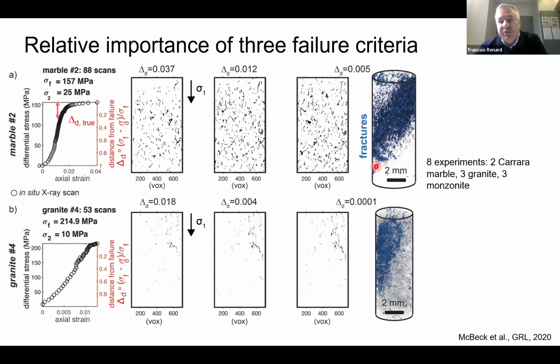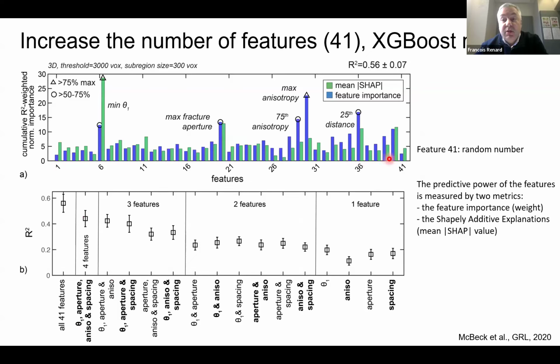And instead of using 14 features, we use 40. And we even added feature 41, which was a random number between 0 and 1. So for each fracture now, we have 40 numbers. The numbers are the 14 as before, the length, the orientation, but we also have the proportions, the 25% largest fractures, 50% largest fractures, some percentiles of the fractures. That's how we reach 40. And then we measure the distance to failure. So we have an R2 value between the predicted and the true distance to failure of 0.5, 0.6. It's not great, but it's still a strong positive correlation between the predicted and the result.